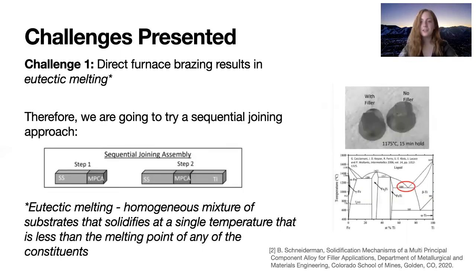So some of the challenges that are currently being presented, one, direct furnace brazing results in eutectic melting, which is not what we're looking for. Eutectic melting is a homogeneous mixture of substrates that solidifies at a single temperature that's less than the melting point of any of its constituents. So what we're going to try to do in upcoming months is to try a sequential joining approach in the vacuum furnace. And here are some of the results we've yielded with the direct furnace brazing prior to our sequential joining assembly.